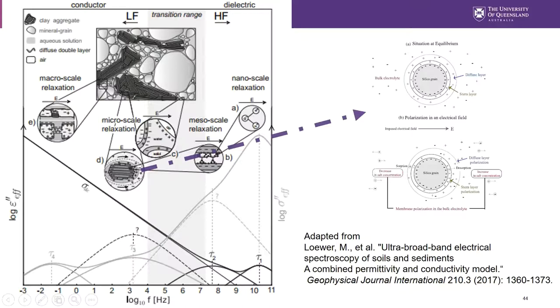Sorry for the internet connection. So if we go into this relaxation, what happens? It's linked to the electrical double layer, the Stern and Gouy layers, because the silica grains are charged negatively, with an excess of charge to compensate that, which is called the Stern layer and the diffuse layer. When you apply an electric field to that structure, it's going to get polarized. What is very important is that ions are going to move tangentially to the surface of the silica grains, and they're going to create this typical relaxation. This is why here we are very sensitive to the chemistry properties and the particle size distribution, because this relaxation is very linked to the particle size distribution.